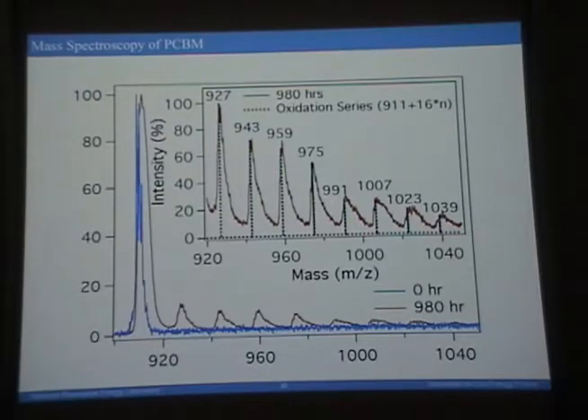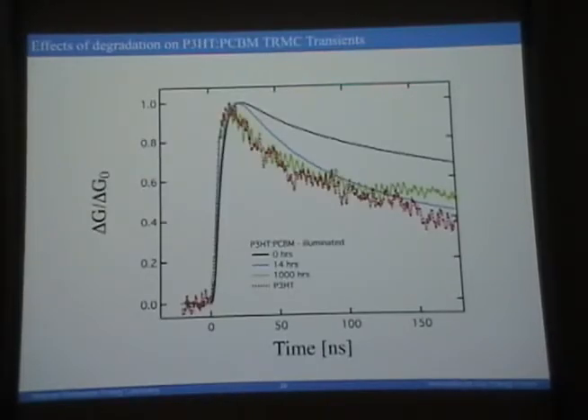Now, my first guess was that you're getting triplet states, you're sensitizing oxygen in the system, you've got singlet oxygen that is attacking the PCBM, but I would have predicted you'd put them all in twos, not singular. So, I digress, because someone enabled me to digress. But we were concerned about the PCBM, because something was happening to the PCBM. It was being oxidized in the true sense of the word, chemically oxidized. And we picked that up using the microwave conductivity experiment.